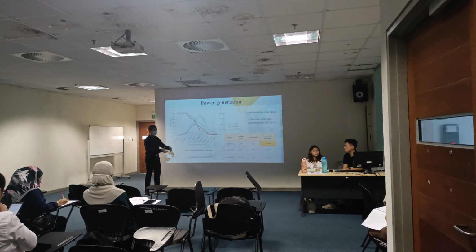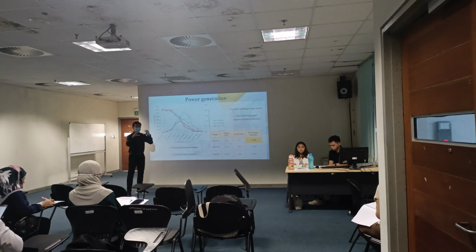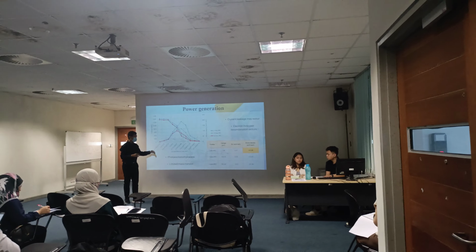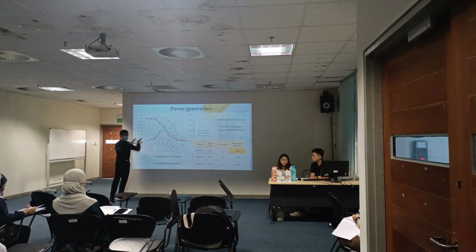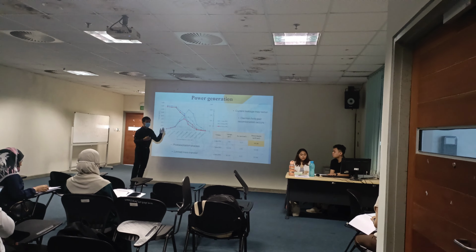Lastly is the limited mass transfer. We know that the formation of hydroxyl radicals is near the surface of the photoanode. When this occurs, a concentration gradient forms there, which leads to diffusion resistance. This diffusion resistance leads to higher internal resistance, thus voltage losses and reduced power output.